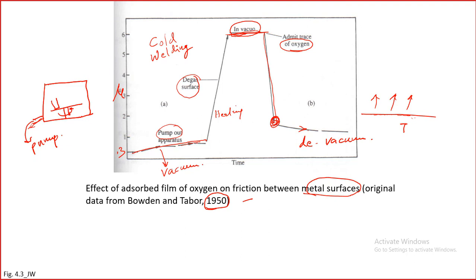So for some amount of vacuum, you see that friction coefficient was rising, but it did not rise too much. But now at this point, what they did in this experiment, they heated. There was some heating element coil inside, and using electricity, they heated the whole surface. Once they heated the surface, the coefficient of friction started rising very sharply. They explained this is because more contaminants were taken out when we heat it. At normal temperature, even by vacuum, not all contaminants will go out. But once you heat it, you provide some energy for the contaminants to get removed.